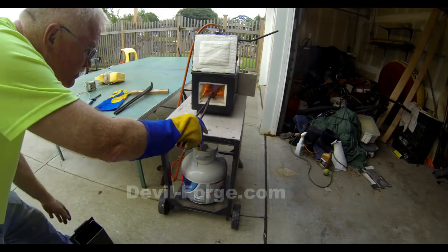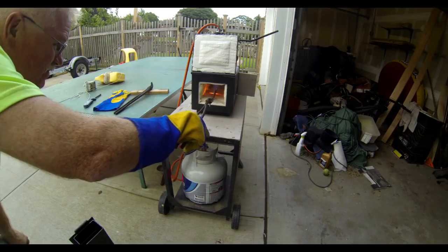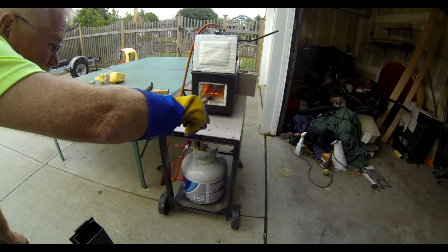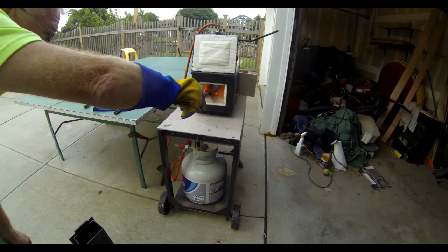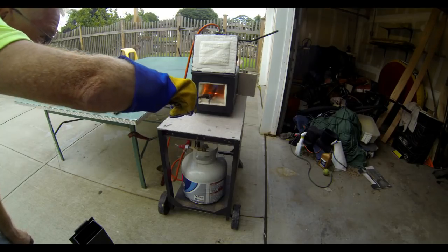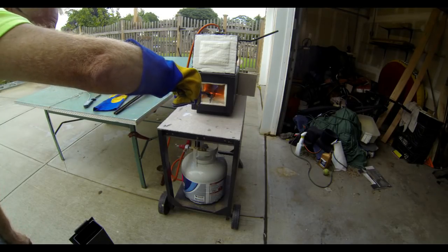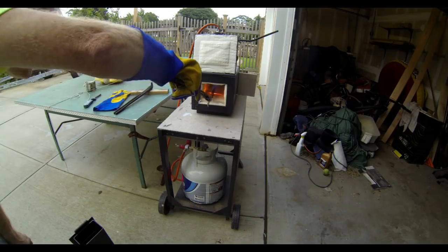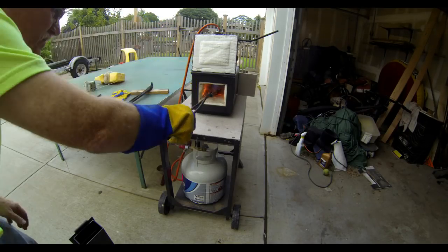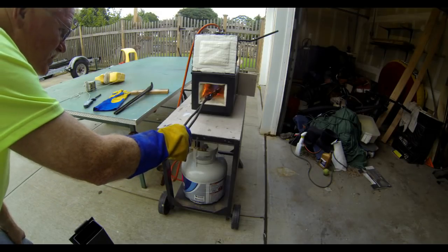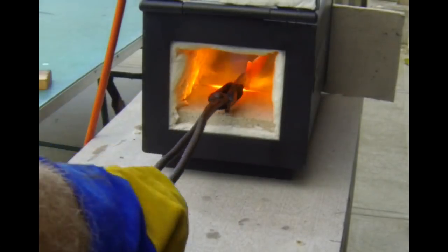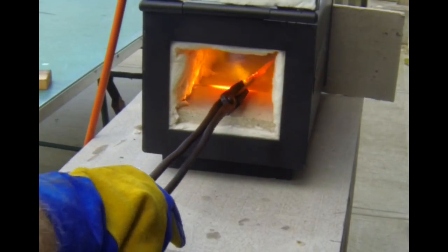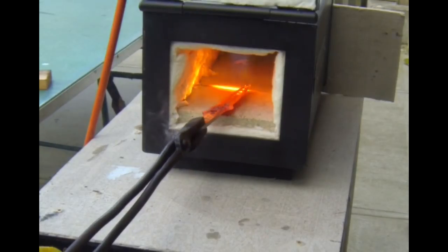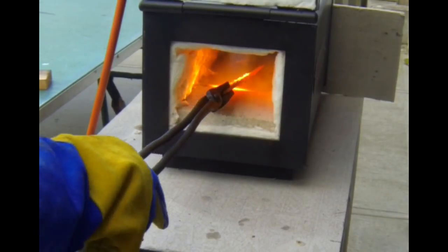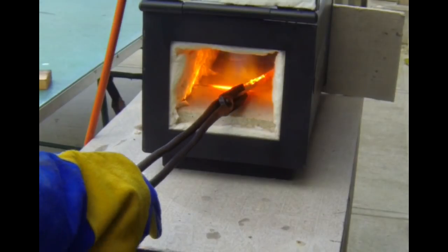And this forge heats up knives within a couple of minutes. Nice even heat. I'm actually only using one of the burners most of the time. I find that if I have both burners on, the tip of the knife gets a little bit too hot. One of the tricks that I learned is, especially with this 1095, you want to bring it up to heat, which is non-magnetic, and then you want to hold it at that temperature for a while, almost a minute. So what you can do is you can take the blade out of the direct flame, hold it off to the side of the forge. It will retain the heat, but it won't overheat.